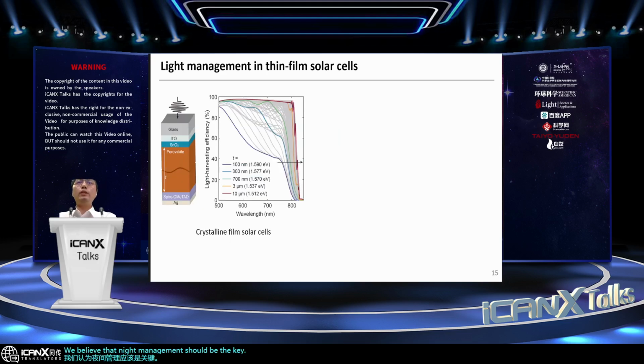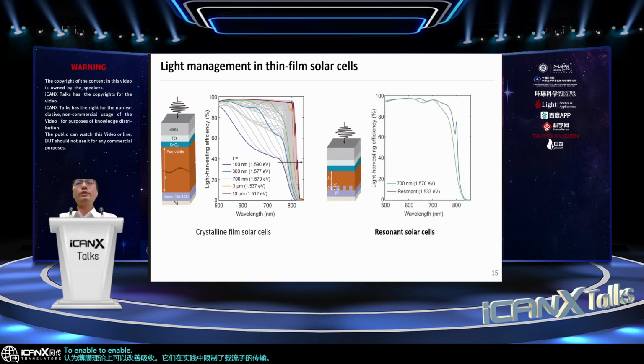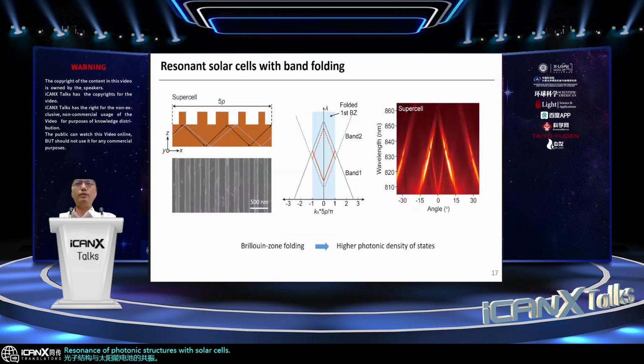For perovskite solar cells, light absorption is still inefficient in thin films, particularly near the perovskite band edge. While thinner films could theoretically improve absorption, they restrict carrier transport in practice. To enable strong absorption, we integrate resonant photonic structures with solar cells. We manipulate the translational symmetry of photonic structures by designing a supercell grating with Brillouin zone folding.